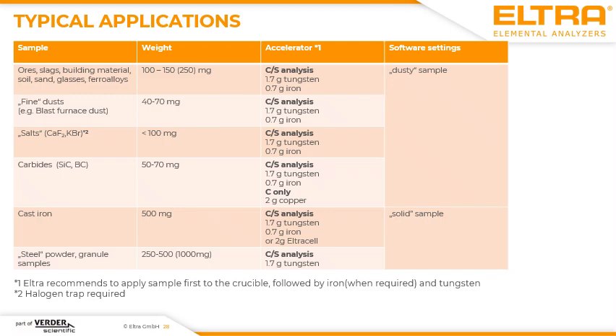When you are faced with the analysis of unknown samples, you will find here a short list of typical samples and the recommended applicable sample weight and the recommended accelerator. For ore, slags, and building materials, typically sample weights between 100 and 150 and maybe up to 250 milligrams are recommended. For fine dusts, which are maybe blast furnace dust, for example, you can also use the same accelerator, but you have to reduce the sample weight down to 40 up to 70 milligrams. It's the same for salts or for carbides. As mentioned before, you don't have to write down this list because I will publish these slides for download, so then it's easy for you to put these slides on your desk.